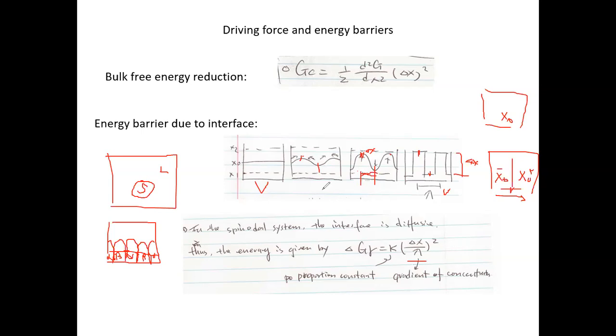We just use this intuitive picture to explain this, but there's a deeper mathematical derivation which we will not discuss. So we can consider that the energy barrier due to the interface is simply proportional to this difference, this gradient of the composition as you travel from one phase region to another. There are higher order terms you can add to this, but this is the first order term.